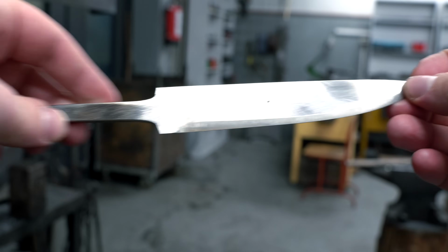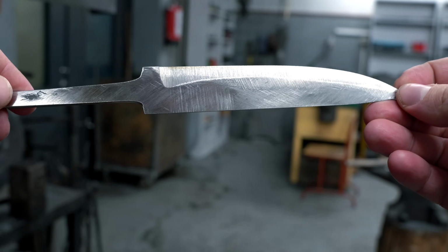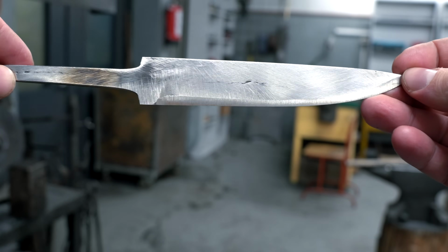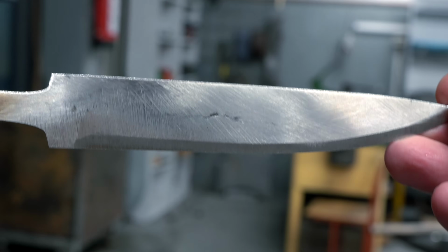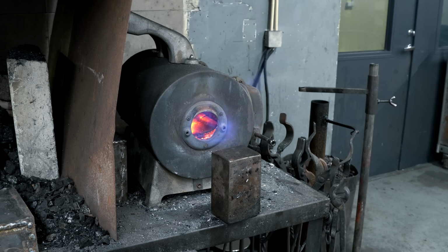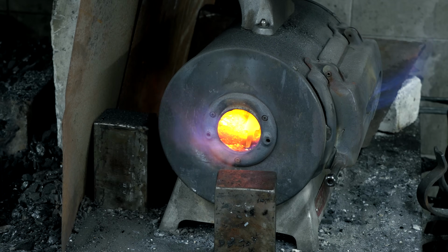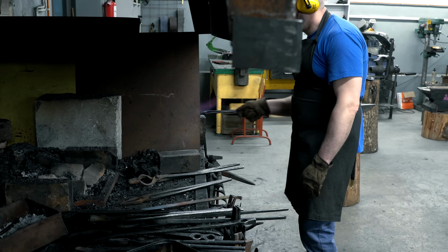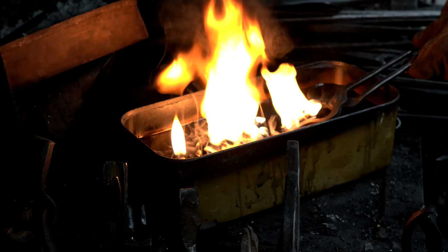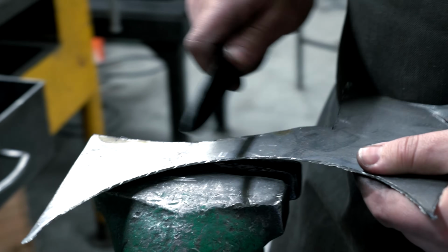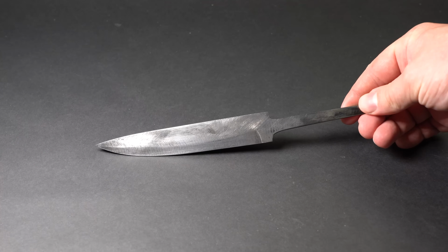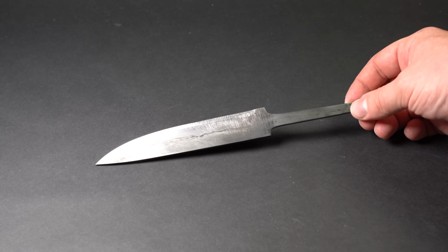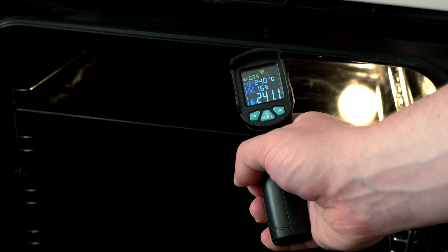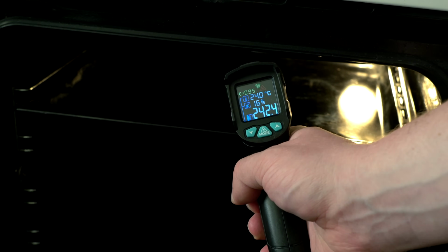As the blade was polished, it became apparent that there were some small defects on the blade because of the unusual shape of my steel nugget, but I think it won't have much of a negative effect on the performance characteristics of my knife. After rough polishing, this blade needs to be hardened, or in other words, it needs to be heated in a furnace until red hot and then immediately cooled off in oil, which will significantly increase the hardness of the material. Nevertheless, besides having hardness, this blade also needs the right tenacity in order for the metal not to break when sharpened or used to cut and not to form cracks. To give it the needed properties, I am sending my blade into an oven for 2 hours at 230 degrees Celsius.